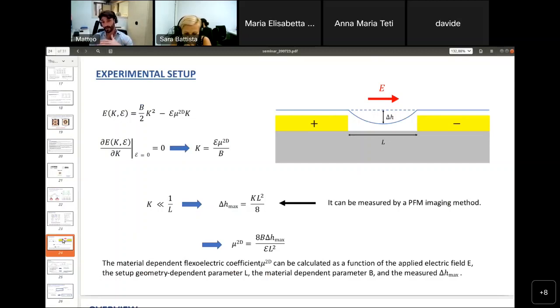That means trying to deposit the two-dimensional material on two electrodes that in turn are laid on a substrate, where the two electrodes are separated by a distance. In this case, the energy function can be written by use of the so-called bending modulus, which is related with the curvature, and the coupling between the applied electric field and the curvature, which by definition is exactly the quantity that we studied in our work.